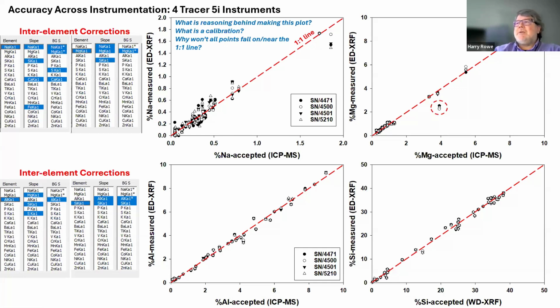All of these instruments are 8 years old too. So it's not all of our instruments, but all that we did this for. So sodium accepted, this is an ICP-MS value versus the value that we get when we take our 41 pellet calibration and apply it to all the samples as unknowns. Sodium, you can see it's kind of sausagey. That's the lightest element, and it's kind of difficult to get a tight measurement, but this is pretty good for samples that are less than 2% sodium.